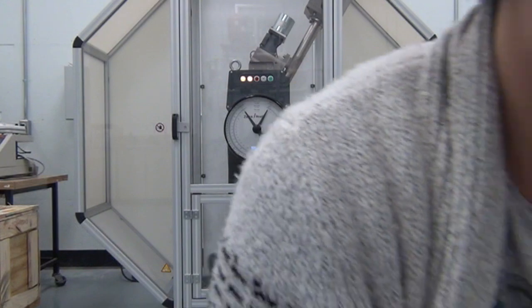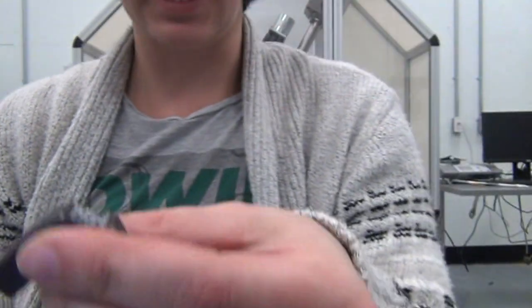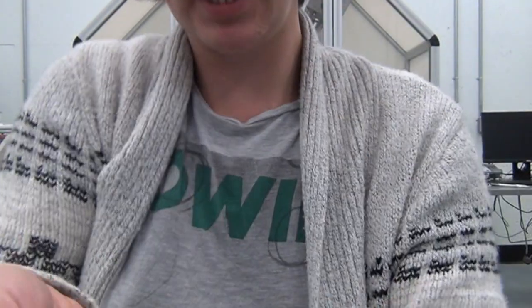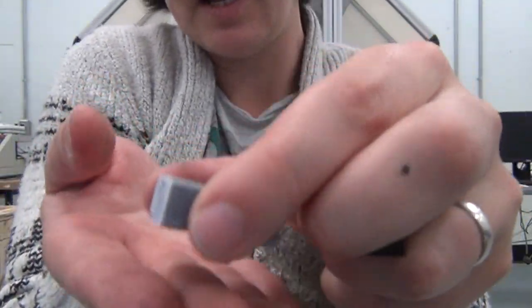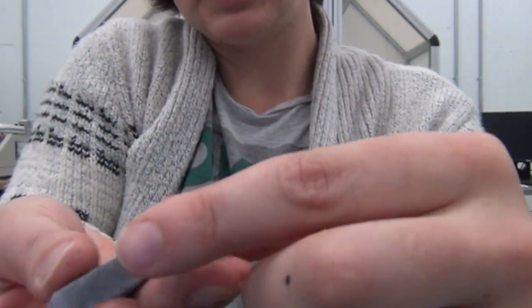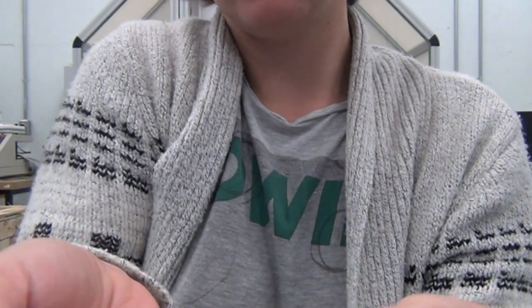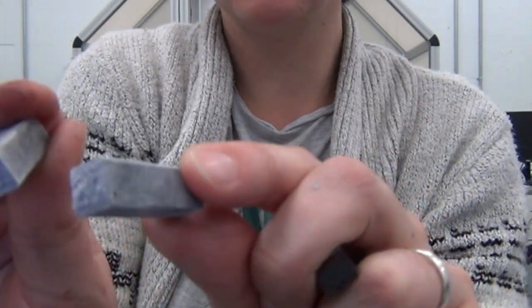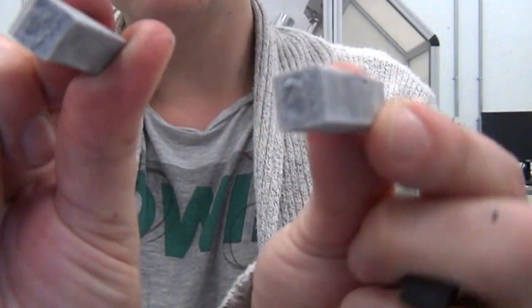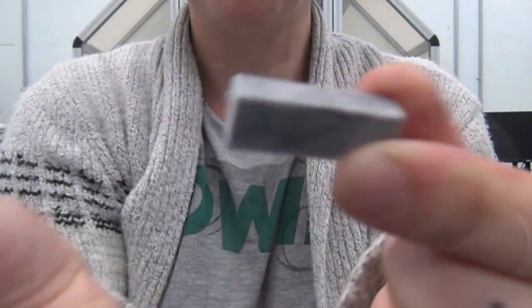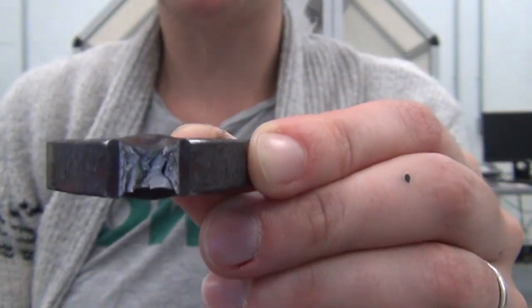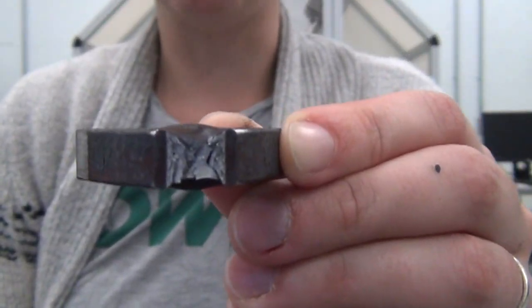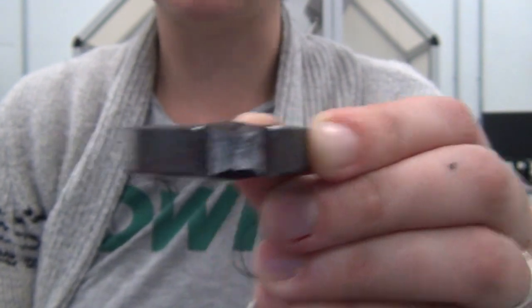So I have my room temperature sample here and I have my dry ice sample. You can see we've got brittle fracture going here. We've got a nice clean fracture surface. It's a straight line across the sample as opposed to the more ductile fracture that we saw on our room temperature and our boiling water samples.